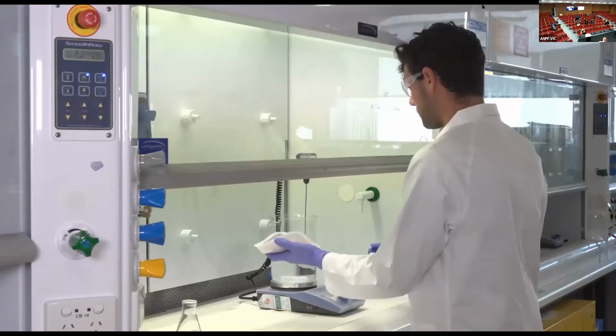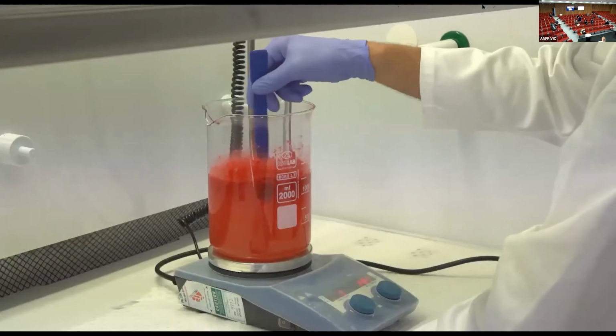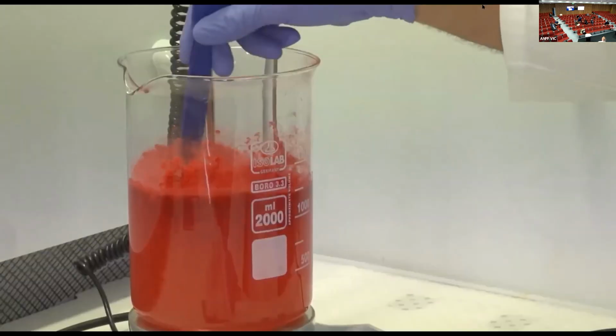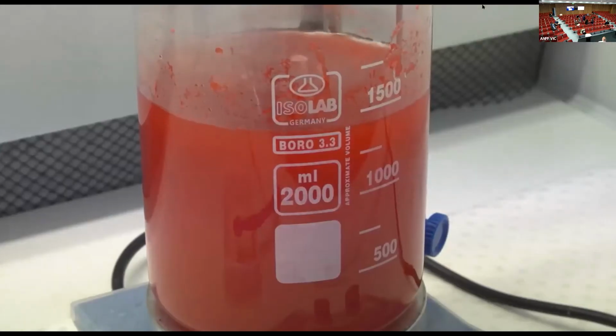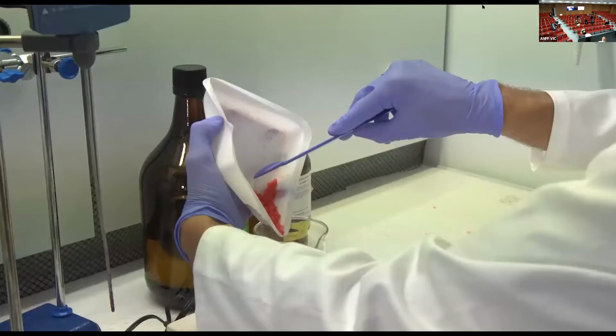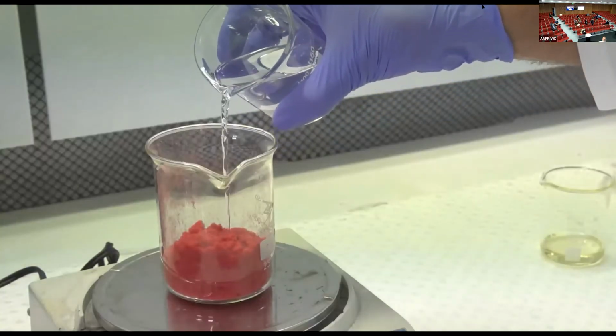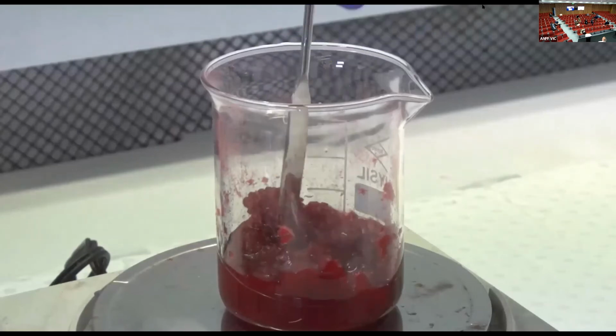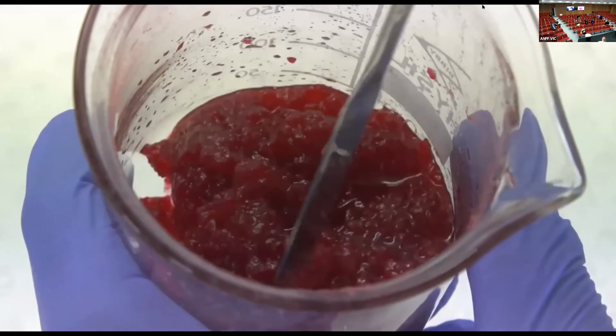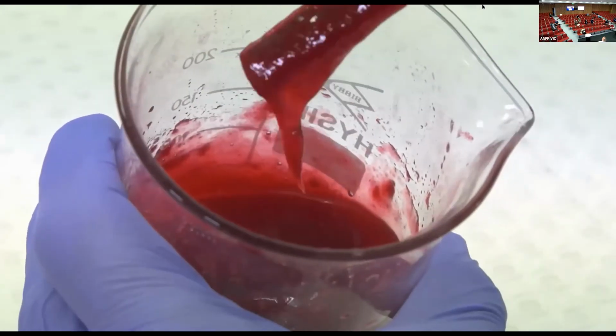The shredded fabric is now ready for pre-treatment. The pre-treatment is necessary to allow dissolution of the cotton. This process is crucial as the chemicals used do not interact with the dye on the fibres. After pre-treatment, the coloured waste cotton is dissolved in a recyclable solvent known as ionic liquid. The result is a viscous honey-like liquid that is ready to be solidified and shaped into fibres.